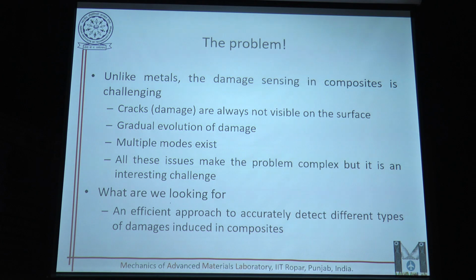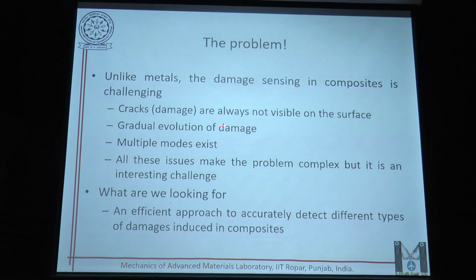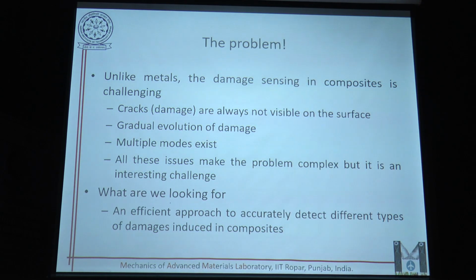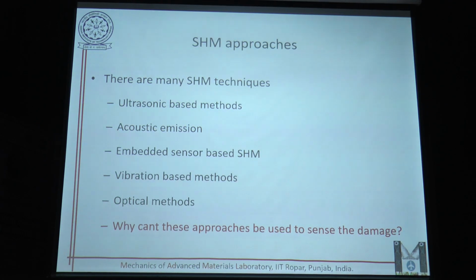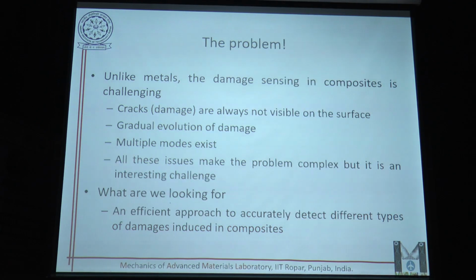The second problem is that many times the delamination is not on the surface, it is in the bulk of the system. So from the outside you don't see it. You see that it is perfectly fine, but inside the damage is growing without you even knowing it. And then it leads to catastrophic failure, because when the damage is sufficiently large, you cannot prevent it anymore. Then multiple modes exist, right? Like I told in the previous slide, there is debonding, delamination, and fiber cracking. So all these make it difficult to detect the damage correctly.